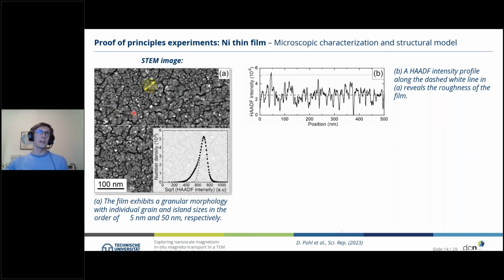And by directly looking at that image, you will see that it's not a continuous film, right? It's more a granular film with small particles forming larger islands of up to 50 nanometers. That you can either see by looking at the HAADF intensity profile or directly by looking at the image itself. So this is not a continuous film as we assumed for simulation.